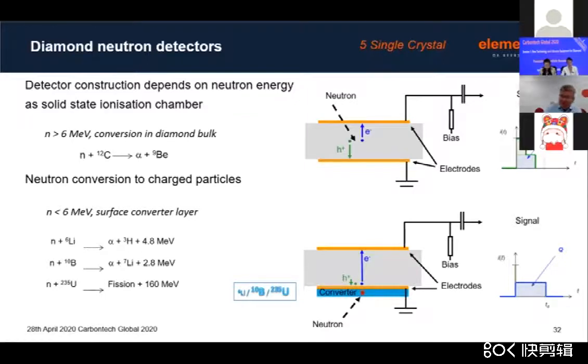You can also use diamond detectors to detect neutrons. Depending on the energy of those neutrons, if they're above 6 MeV, you can actually break the diamond down itself, and you can measure the charge that's generated from that. And again, you can use the drift velocity of the electrons and the holes to tell you something about the energy of that neutron. And equally, with lower energy neutrons, you have to use a converter layer that you attach to the diamond that generally generates an alpha particle and generates electron-hole pairs. And again, you're able to use the drift of those to tell you about the energy of those particles.